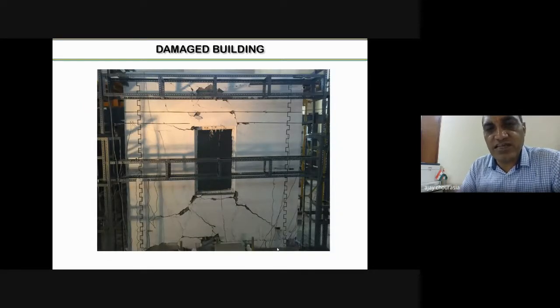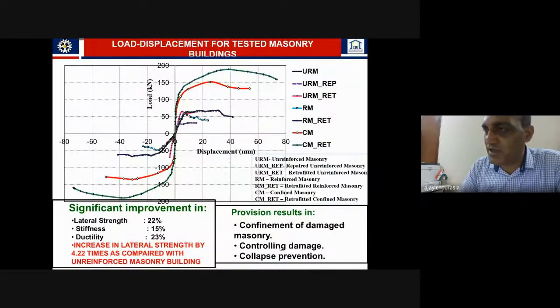So this is the typical damage pattern noticed after the retrofitted confined masonry model was put under lateral displacement-controlled cyclic loading under quasi-static condition, that means under a very low frequency. This type of crack pattern was similar to the crack pattern we normally see after any earthquake event in a realistic state. So we could achieve the realistic scenario through the experimental investigation by adopting a proper experimental protocol, and the damage data was recorded in terms of deformation and strains by LVDTs and strain gauges, and the data thus collected was analyzed and put for comparison.